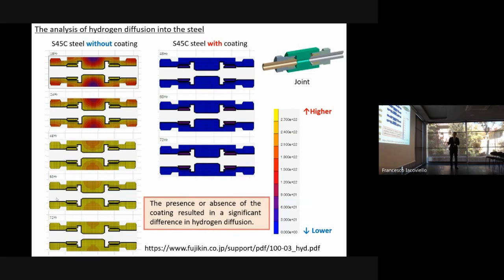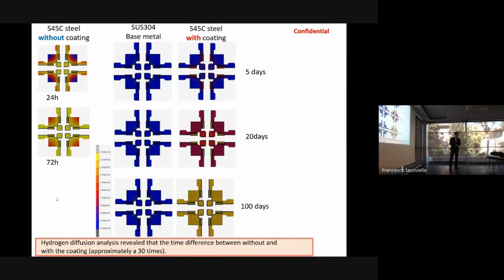Next, the analysis of hydrogen diffusion into the steel. These are the joint models without coating and with coating. The presence and absence of the coating result in a significant difference in hydrogen diffusion, which is quite low. And this is the other type of joint, I think, without coating. There is about 30 times slower hydrogen diffusion.